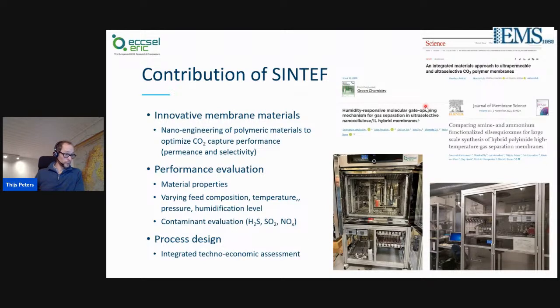We contribute quite a bit on performance evaluation within the projects that we have ourselves, but also for companies that come to us for third-party verification of their membrane technology. And then we typically evaluate the material properties as a function of feed composition, temperature, pressure, different humidification levels, and especially also can test the effect of contamination of the flue gas, for example, on the membrane performance. The picture here, you see some of our lab equipment.